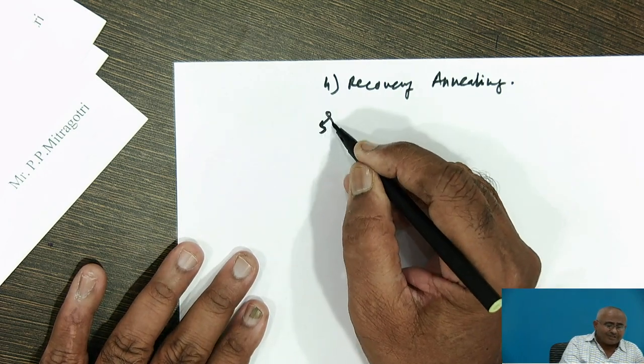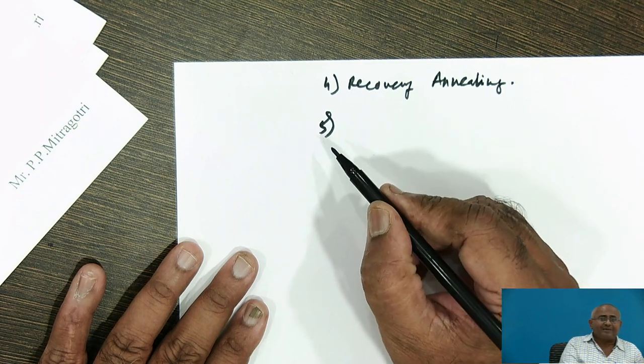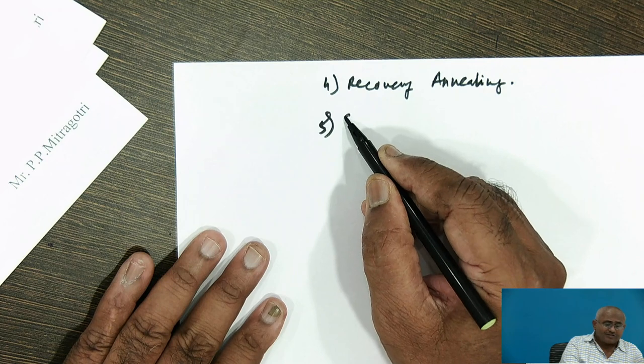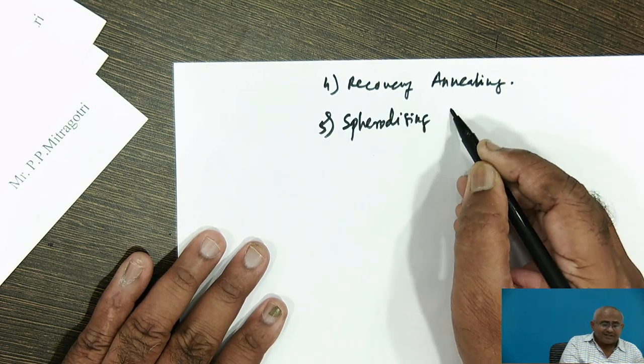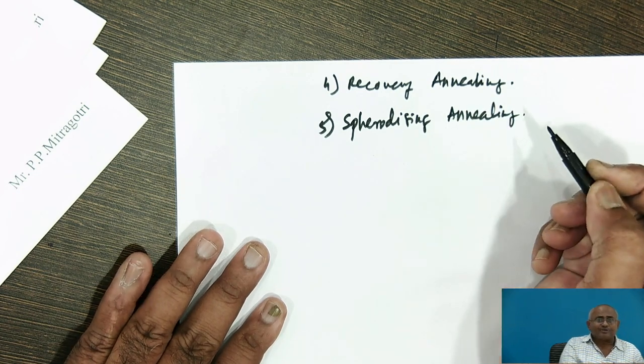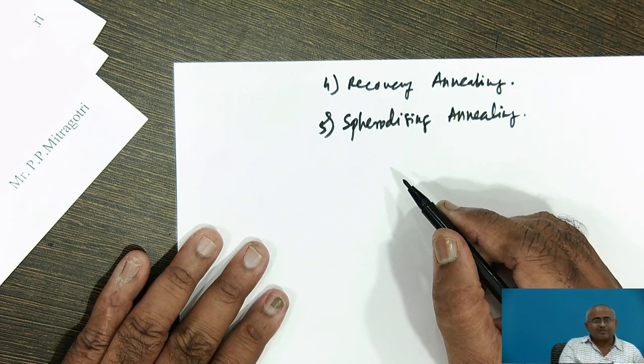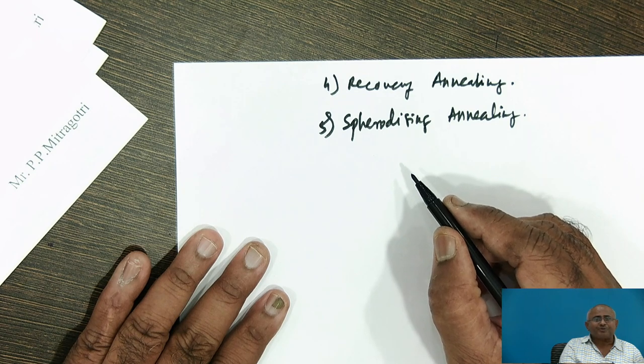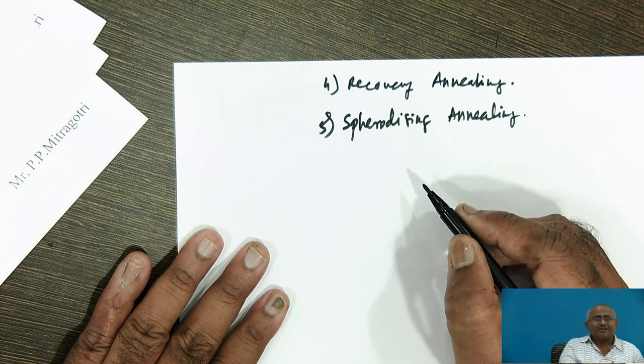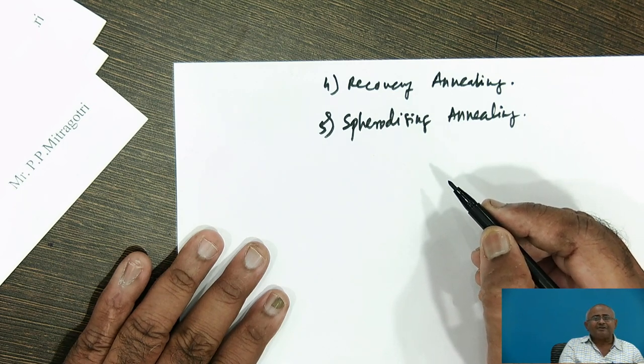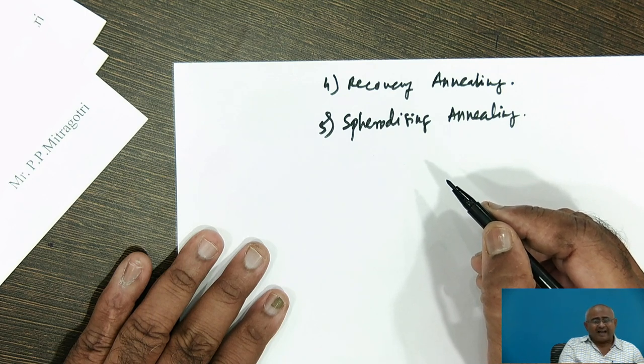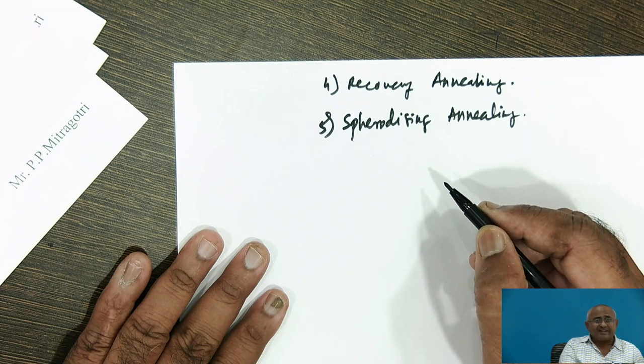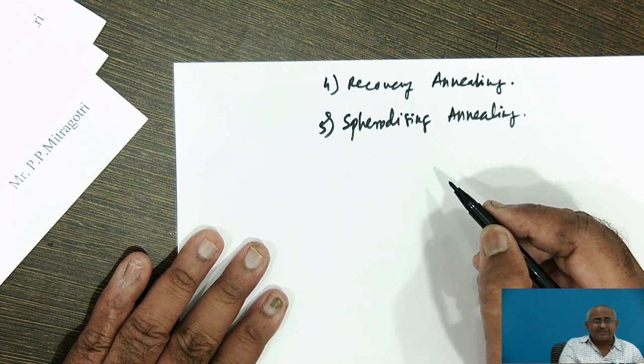The next annealing process is important for improving machinability of hypereutectoid steel and tool steel — that is spheroidizing annealing. In hypereutectoid steels and alloy tool steels used to manufacture dies and tools in processes like forging and extrusion, machinability is very poor. We are unable to machine these to required tolerances. Therefore, we need to spheroidize the pearlite present and break the cementite network and carbide network present around pearlite grain boundaries, and that is achieved by spheroidizing annealing.